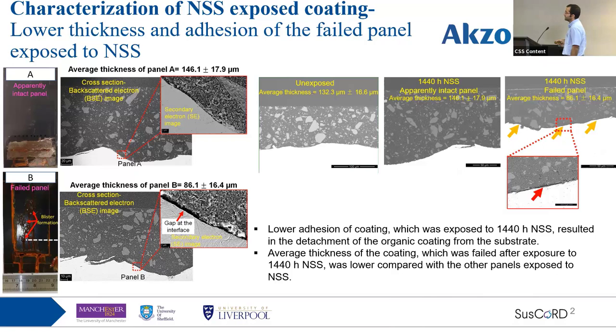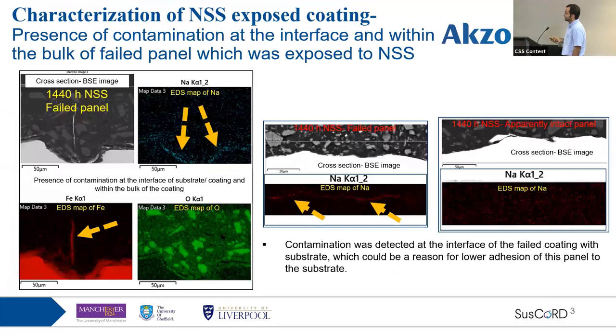And also we observed that there is a detachment at the interface of this coating with the substrate, which does not exist on the unexposed samples and the other samples exposed to the neutral salt spray test, which could indicate lower adhesion of the coating to the substrate. But why? What has caused this lower adhesion? In order to find out, I started doing some EDS analysis and EDS mapping of the interface regions of this coating, and I could detect some kind of contamination on the surface. As you can see, I have detected sodium at the interface, but also I have detected iron within the coating,